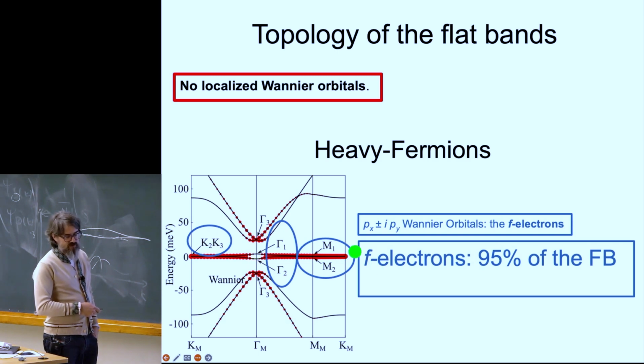There are 8 of them, but per spin, there are 2 of them. These are good quantum numbers per valley. So you look at these flat bands in the non-interacting picture, and the first thing you do is establish their topological properties. These can be established in many ways, actually. It turns out that there's a stable topology here that's given by the Wilson loop. But there's a simpler way, if you want to understand the basic levels of the topology: you get the high symmetry point eigenvalues and plug them into the Bilbao Crystallographic Server, and it gives you a topological index that's non-zero. Basically, this type of eigenvalues can never be described by an atomic limit.